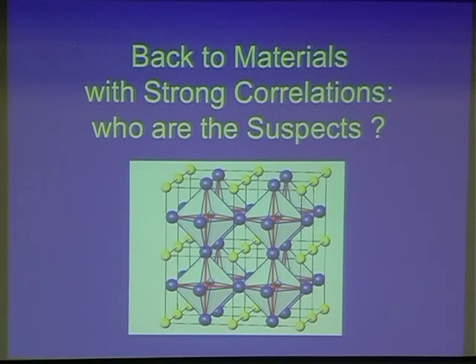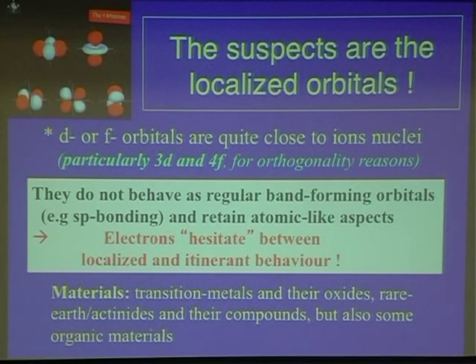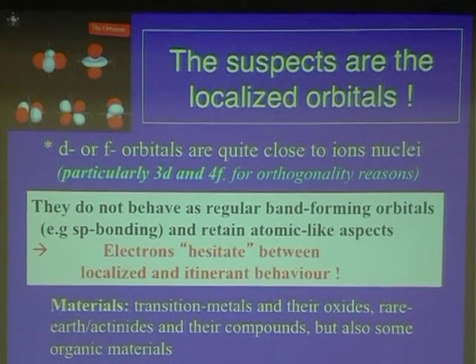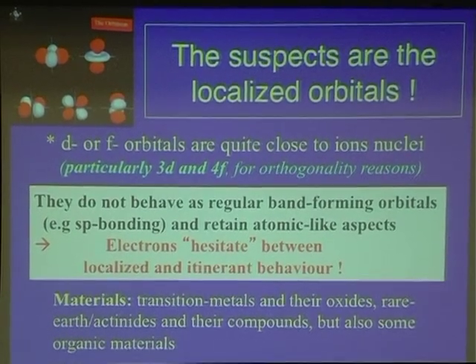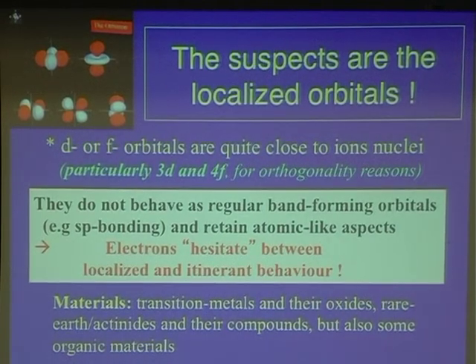But let's now go back to materials, to the materials of the chemist with strong correlations. I've mentioned the existence of such materials, but I haven't told you who the suspects are, what they really are. Well, the suspects are materials in which the orbitals in which the electron lives are fairly well localized around nuclei. And you can guess why this is the case. If these orbitals are reasonably well localized, the tunnel amplitude between different atoms will be small. And also, the matrix element of the Coulomb interaction will be fairly large because there will be relatively limited screening. So we will go into regimes where the matrix element U can be significantly larger than the individual hopping matrix element and will reach this strongly correlated regime.